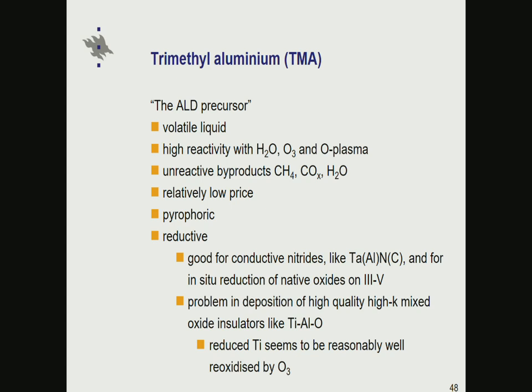Volatile liquid, high reactivity with various kinds of co-reactants, unreactive byproducts being produced, available at a relatively low price. The main problem is that it is pyrophoric, but that's a sign of ALD reactivity. One thing which is not necessarily so obvious and well known about TMA is that it's quite reductive by its nature. So it's good if one wants to make conductive nitrides like tantalum aluminum nitrocarbide. I will come back to that later.